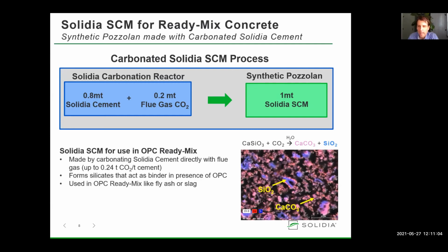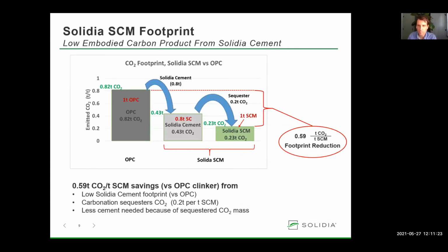The carbonation reaction for making Solidia SCM is the same reaction that occurs when precast Solidia concrete is made. Calcium silicate plus CO2 forms calcium carbonate and silica. The silica, which forms at the surface of the SCM particle, acts as a binder in the presence of OPC. Like precast Solidia concrete, Solidia SCM has a lower CO2 footprint than OPC-based products.